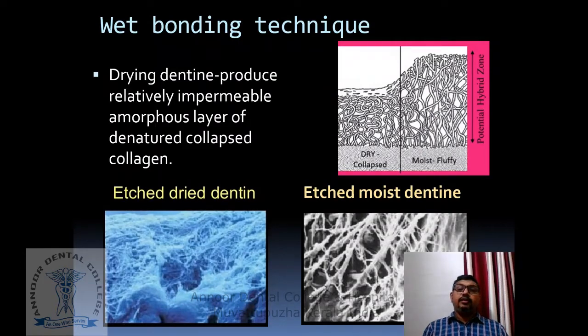Okay, so you see this picture. What happens is when you dry the dentine after acid treatment, the collagen meshwork will lose its water. It will collapse. The surface will become an impermeable amorphous layer of denatured collapsed collagen that cannot be penetrated by your adhesive resin. So the bonding will be a feeble bonding on the top surface alone, whereas if the collagen meshwork is wet, as you see in the right picture, the bonding agent will penetrate into the collagen meshwork, and there will be a layer of demineralized dentin that has been infiltrated by resin material. That is called the hybrid layer.